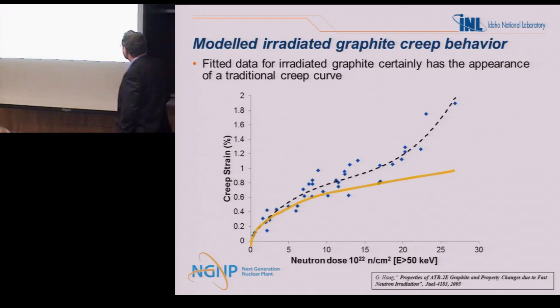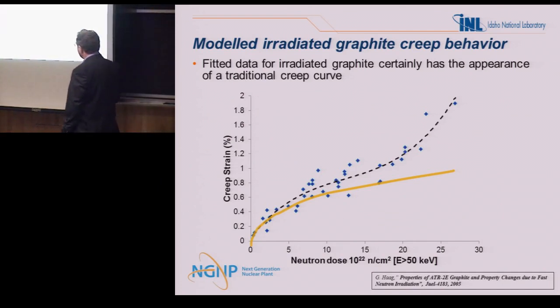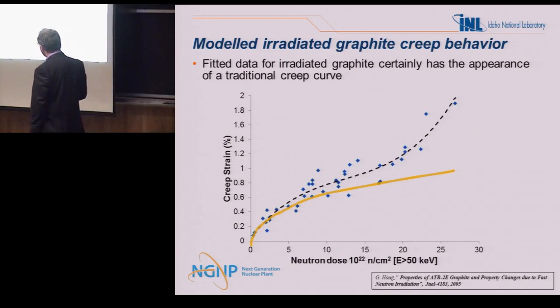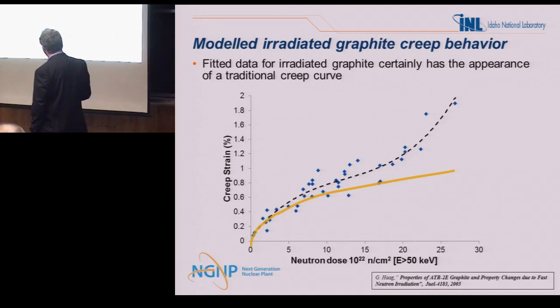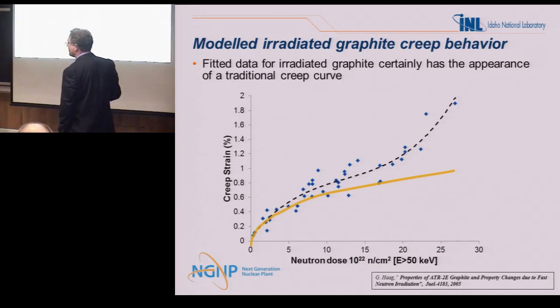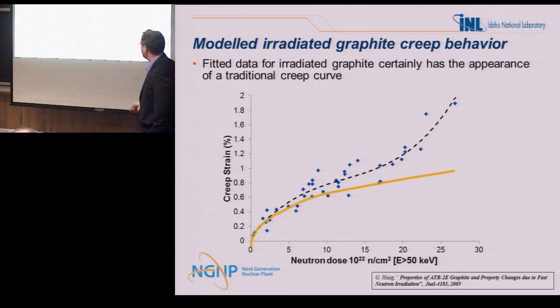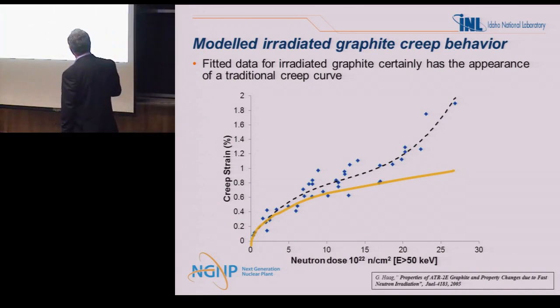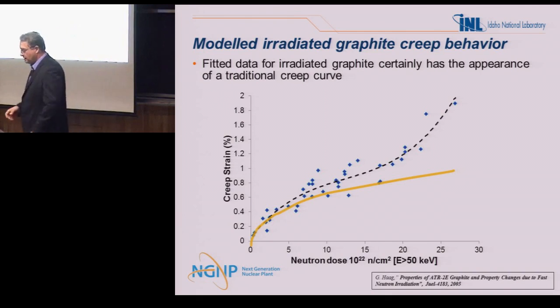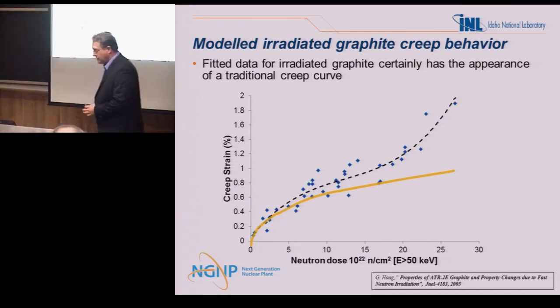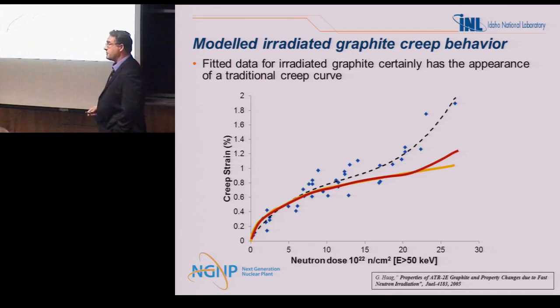And this is what we get. And it's about the best we can get. And it's really nice. We get a nice short primary creep, and then we kind of get a secondary creep. I just sketched this on top. But what you can see is this is viscoelastic, and you get a steady state creep, and then all of a sudden it just sort of peters out. It doesn't really match the tertiary creep. So we went in and revised the model, and we can get it a little bit better, but it's not really all that great.